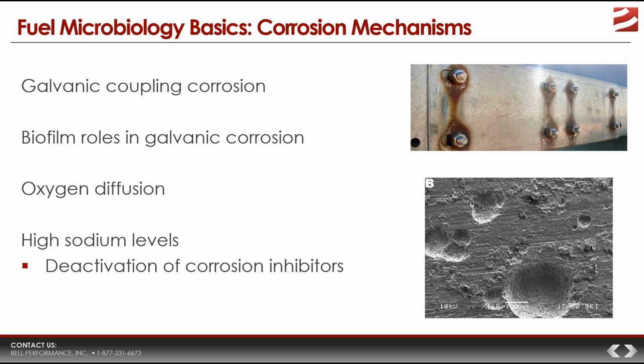So what happens here is, through the principle of osmosis, things like to move, provided there is a way for them to move, from areas of high concentration to areas of low concentration. And so when you get water and fuel, oxygen will want to diffuse or move from the fuel, where it's high concentration, into the water phase to try and even things out. Now, that in and of itself is not a big deal. But when you have biofilm that's nearby, oxygen will actually get trapped by the biofilm, and you will get a localized area where the oxygen concentration is pretty high. That produces localized corrosion and metal loss.